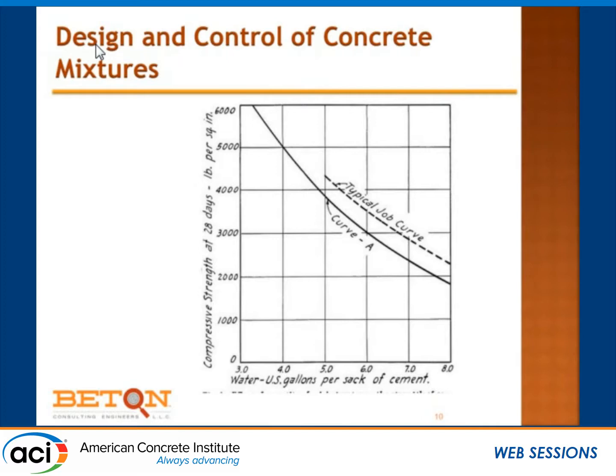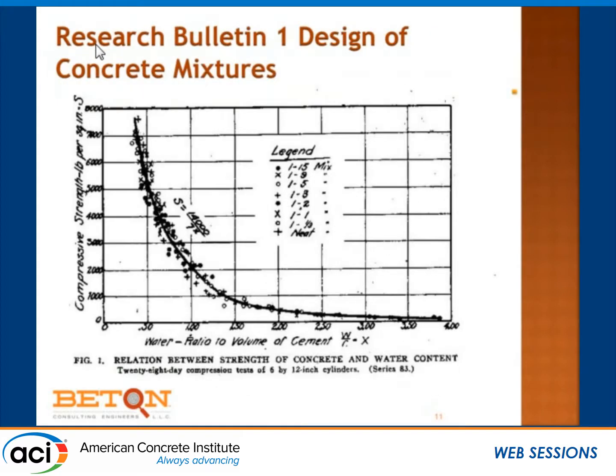He used a very different number, and so this type of curve is one that you see and that people will put together. This one's a little older, so it's presenting the water cement ratio in U.S. gallons per sack. But this particular one is old. An older one is the one that Abrams himself published. Now, he looked at mixes that were from neat cement paste all the way up to one part cement, 15 parts of aggregate, and this was the relationship between strength of concrete and water content as published in the research bulletin number 1 of the PCA in 1918.